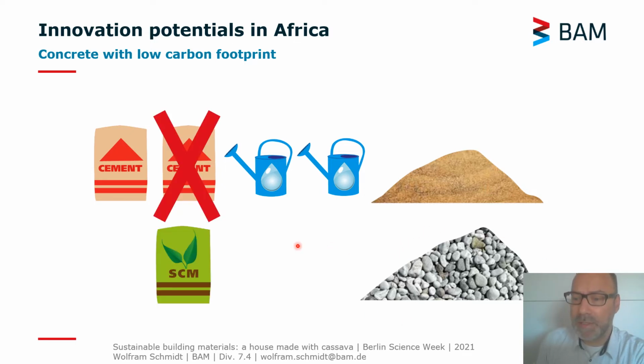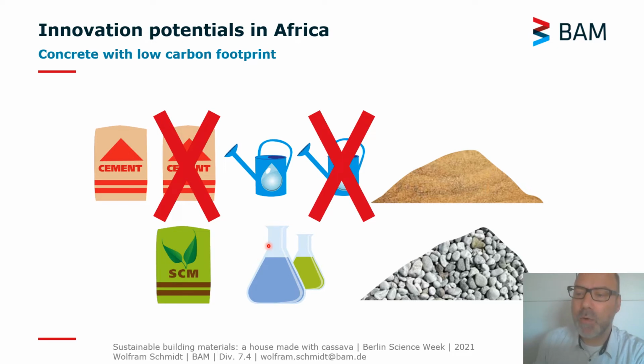Now, in order to make concrete greener, to reduce the carbon footprint, we have to minimize the amount of Portland cement clinker that we are using in our binder and replace it with so-called supplementary cementitious materials, which have a lower carbon footprint. And in addition, the more water we add to concrete, the lower the strength and the worse the durability will be. So we have to find ways to minimize the water content in concrete, and that requires chemical admixtures. Also, these chemical admixtures can contribute to compensate for some negative aspects, particularly with regard to workability of those supplementary cementitious materials.